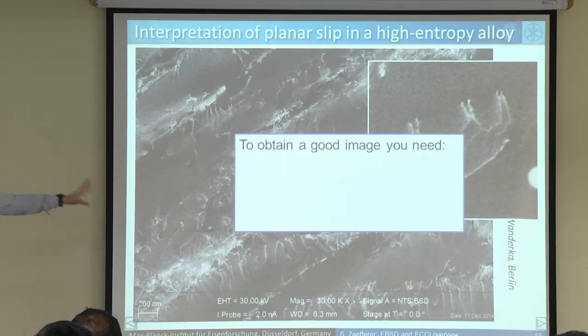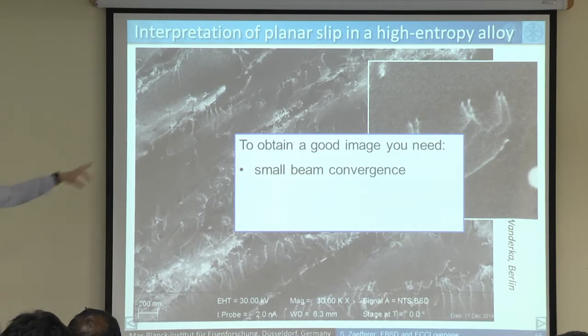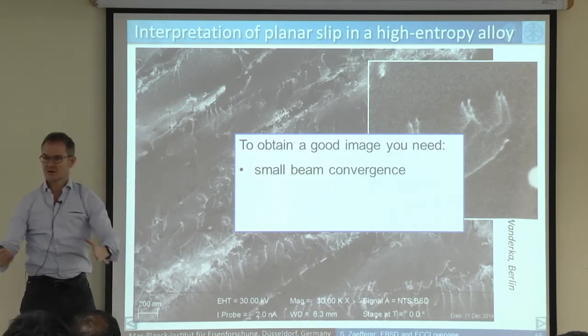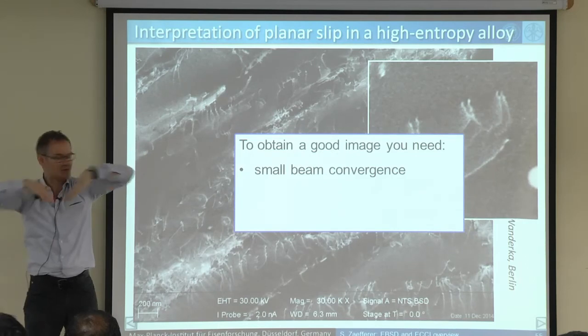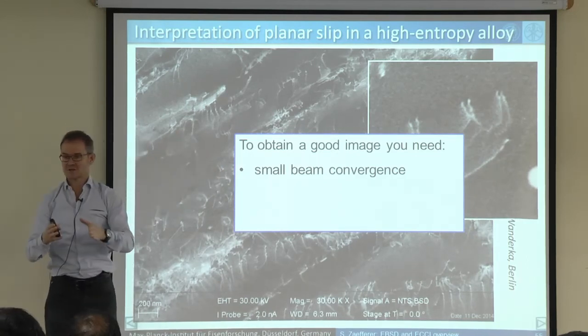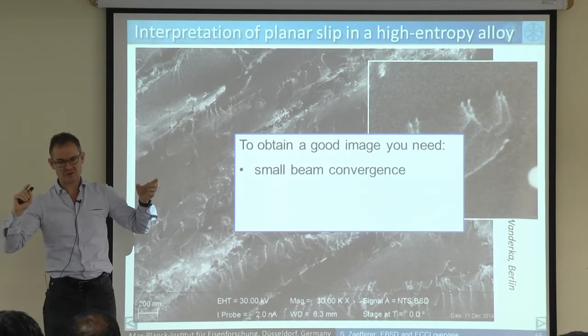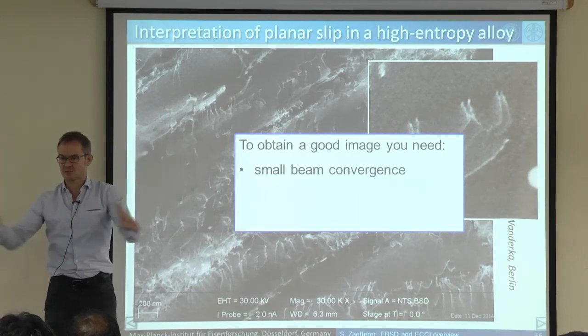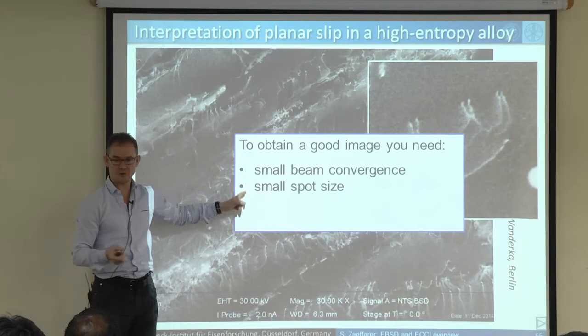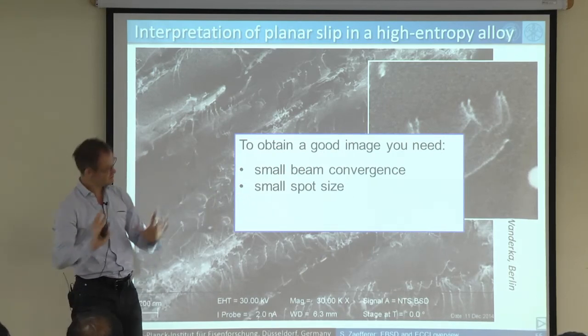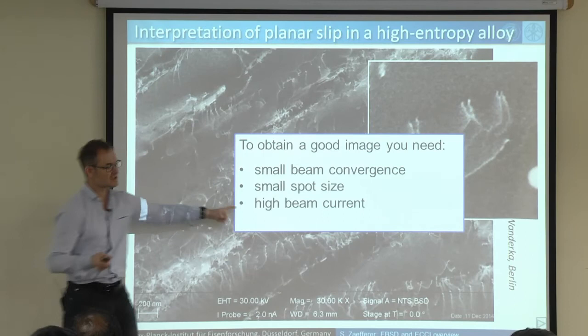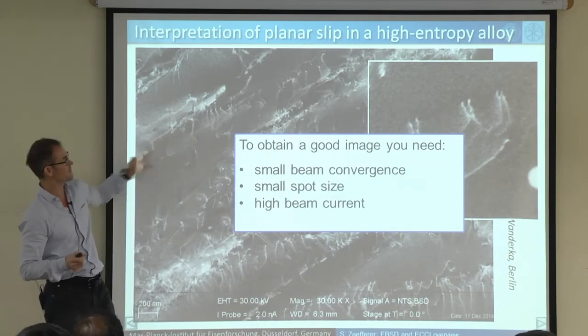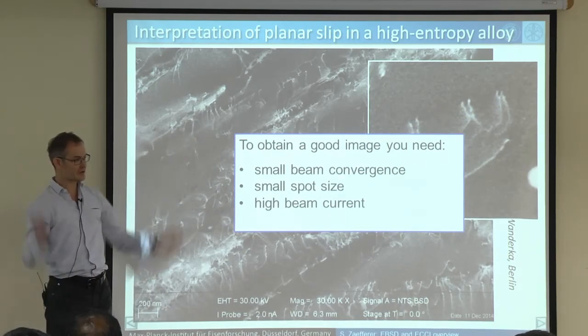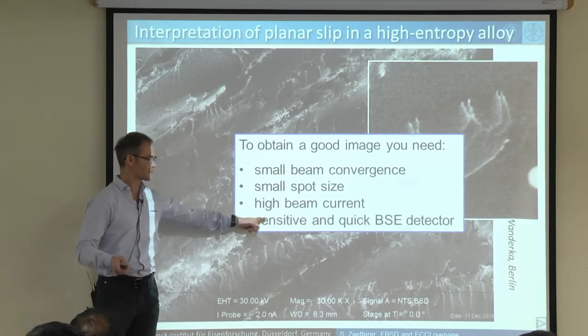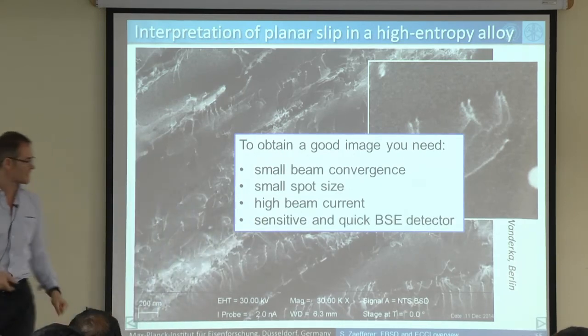Just shortly, let me give you an indication of what you need to make this beautiful ECCI. Like in TEM, you need a parallel illumination. Usually in an SEM you're using convergent illumination. You need parallel illumination here, which is not so nice because when you have parallel illumination your spot becomes wider. So you want a small spot size at the same time, parallel and small. This is difficult to organize. And you want it at high beam current because this is a relatively weak technique, so it needs a lot of power. And finally you need a sensitive and a quick BSE detector.